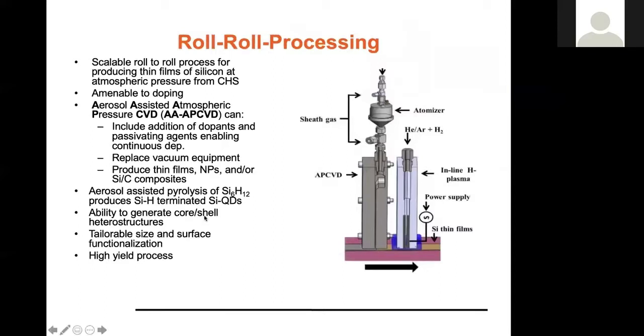This roll-to-roll processing is attractive for a variety of reasons. In a continuous process, you can have fabrication of your entire device. And due to the unique reactivity of CHS, you can co-add dopants. If you want to make a doped silicon or a silicon-carbon composite, you can feed both reactants in simultaneously, do the deposition in real time in a single step, and yield the desired product in a high-yielding way.